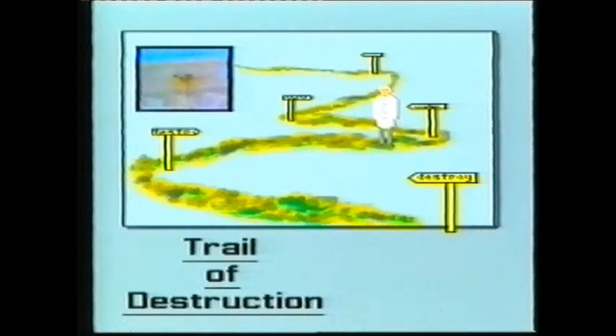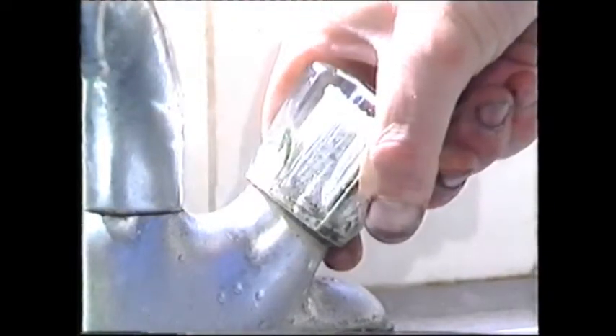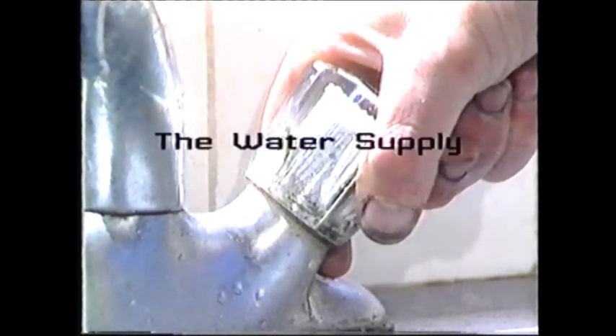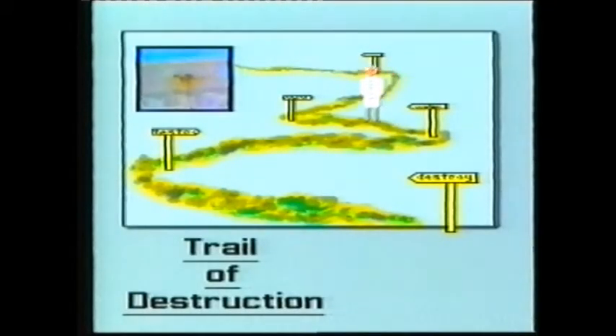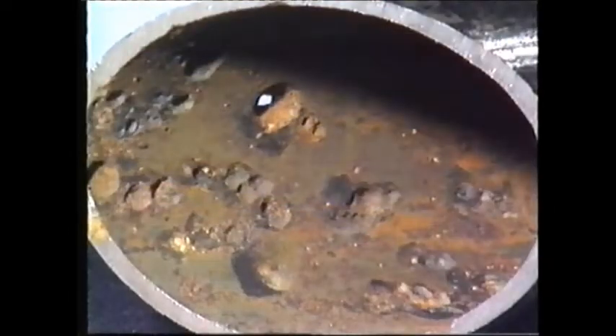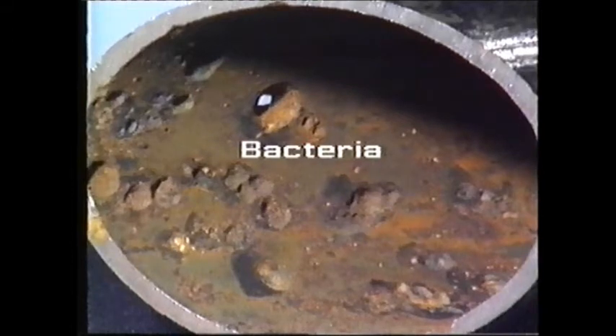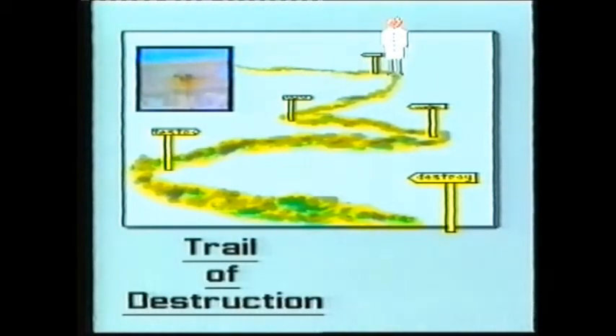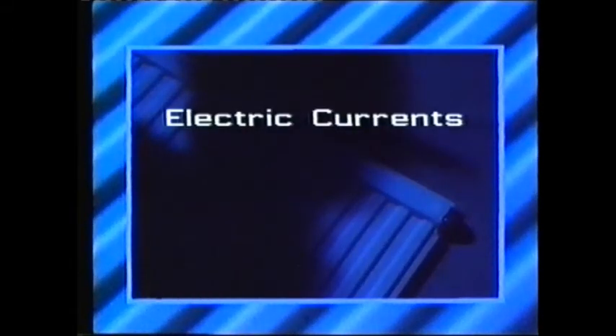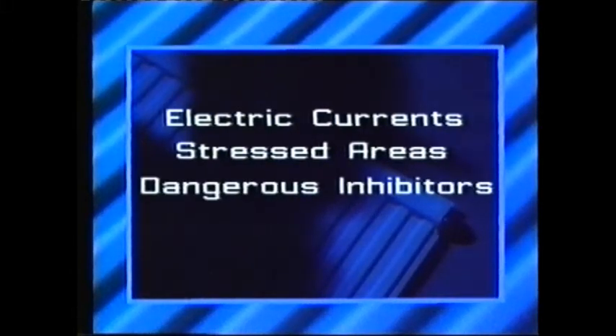Another cause of corrosion is the water supply itself, the corrosiveness of which depends on its chemical makeup. High levels of chlorides and sulfates increase corrosiveness, and indeed soft waters are more corrosive than hard waters. Corrosion is also promoted by bacteria. They're particularly active under debris and can cause perforations even in heavy gauge steel. These and other causes of corrosion, such as electric currents caused by leakage faults, stressed areas in steel, and even the use of some dangerous corrosion inhibitors, which can themselves tolerate or cause localized corrosion, all lead to this. Black oxide sludge, formed from the metal that should still be part of the radiator.